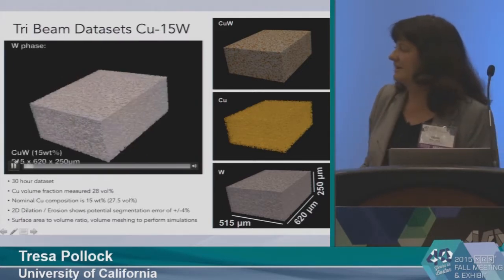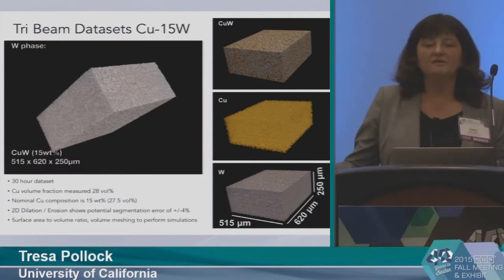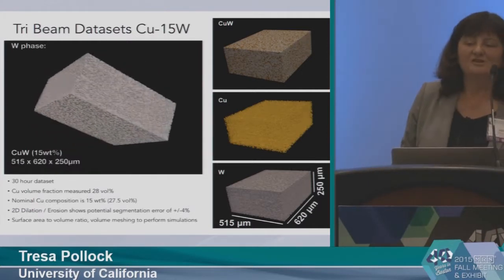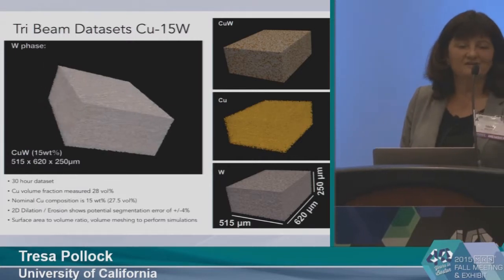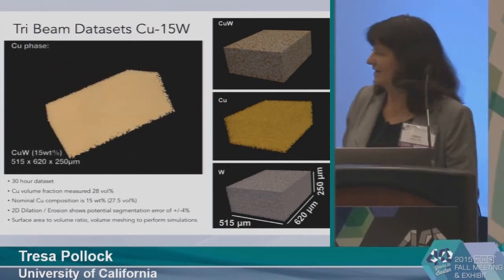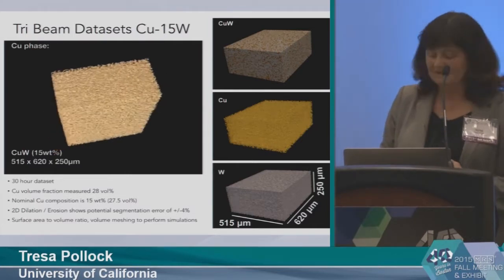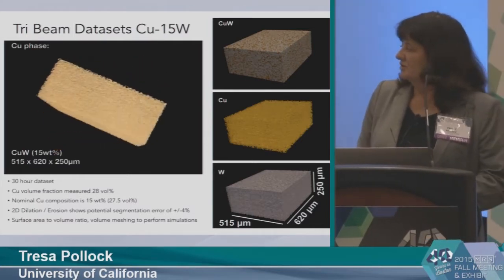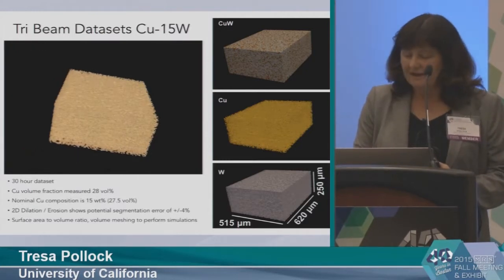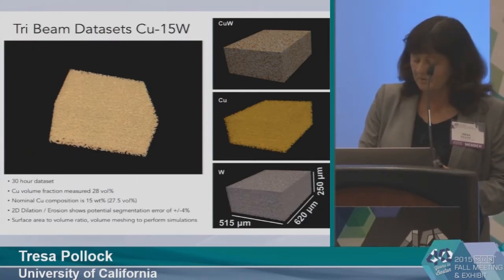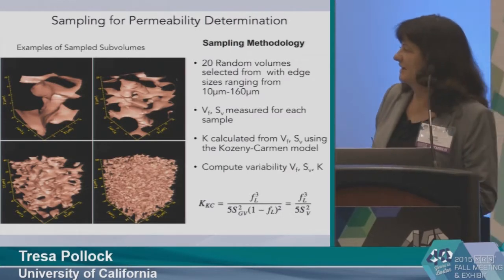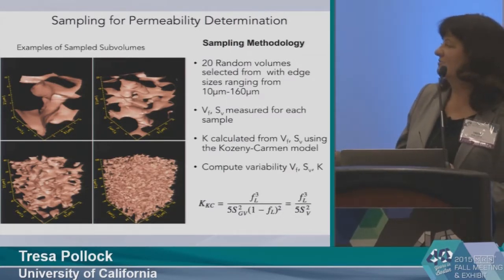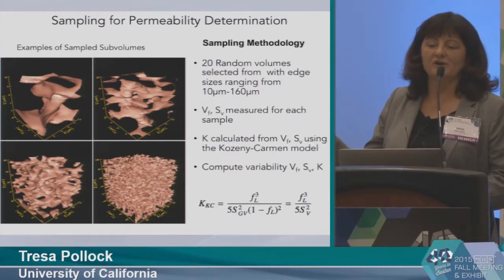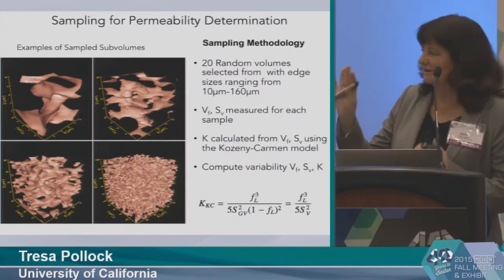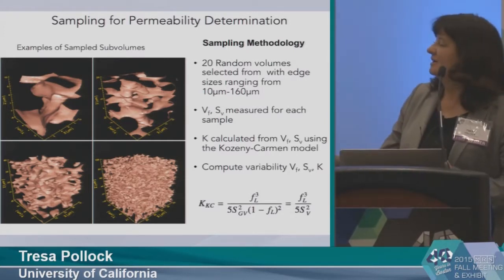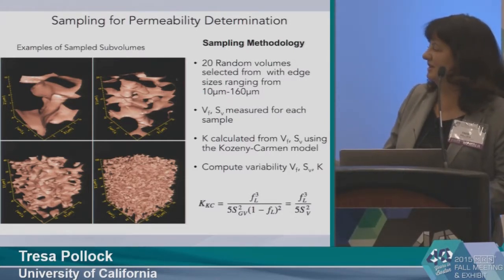And then we, again, have a data problem because in every slice, there's about 1 gigabyte of information, and these data sets, depending on how much information you gather, can quickly become terabytes in size. That does bring up the question, how much information is enough? And that goes back to, well, what property do we want to predict? And so in this case, this material, you sometimes intentionally use it and ablate the copper out for cooling purposes in hypersonic vehicles and things like that. Details don't matter. But what I show here is the big data set with subsamples.